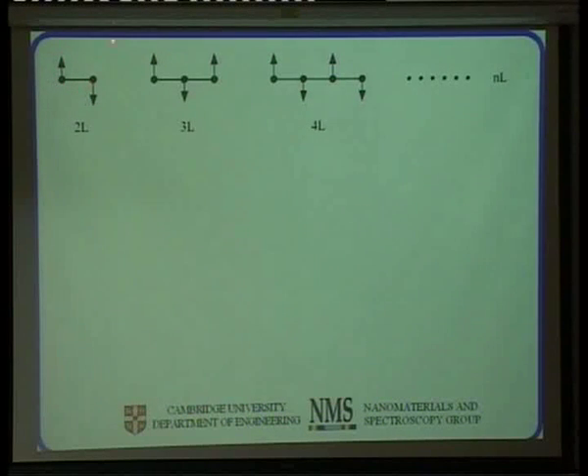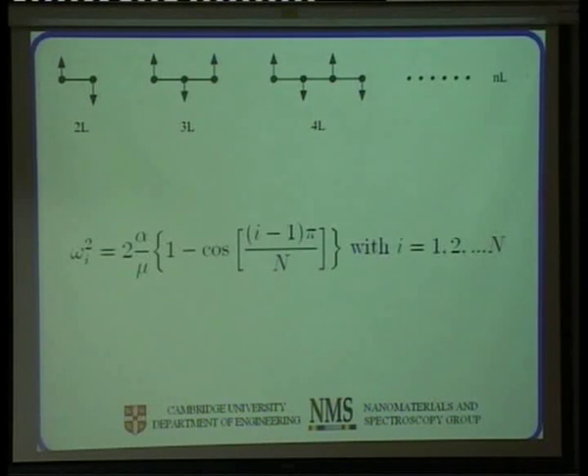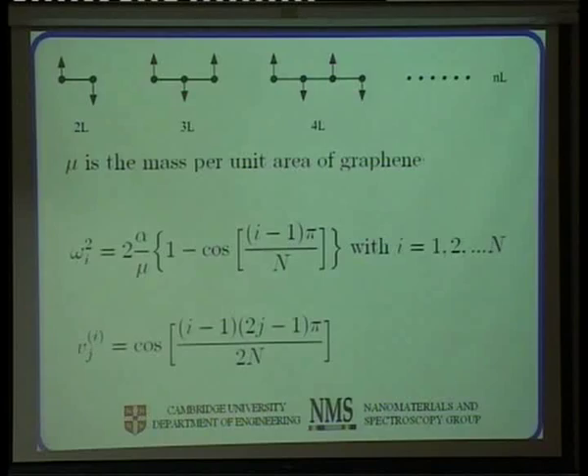This is a relative motion of 2 planes, and you can model it as a ball and stick model with some spring constant in it. And there is a very, very simple formula that you can extract by hand that gives you the frequencies as a function of the number of layers. And it also gives you the displacement. The only 2 unknowns are the mass per unit area of graphene, which is not really unknown, and the force constant per unit area, which may or may not be unknown, so the interaction between the planes.